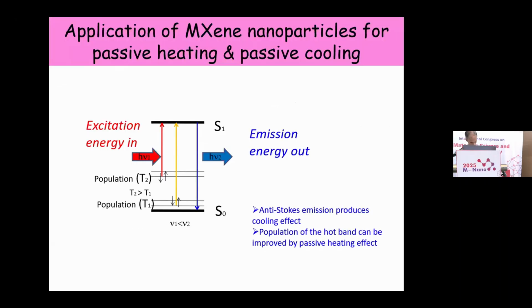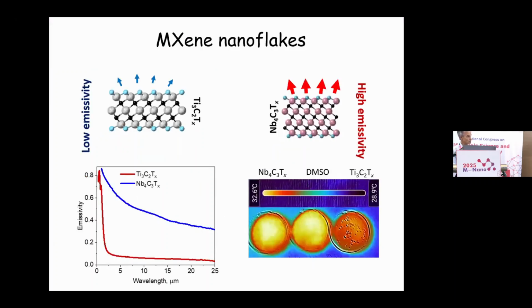So finally, in the third part of my presentation, I would like to tell about interaction of MXenes and infrared dyes. A specific feature of anti-Stokes emission is that in principle it can produce a cooling effect, because we deal with absorption of a lower energy photon but emission of a high energy photon. That means that part of the energy is removed from the system, and the system can be cooled down. And also we can apply specific nanoparticles which produce a passive heating or passive cooling effect. And these nanoparticles are MXenes. Particularly, we used titanium and niobium MXenes.